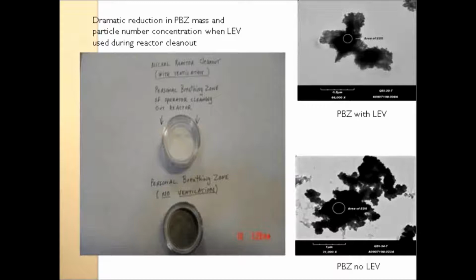Whereas when they didn't use it, look at what happens. This is breathing zone samples. You can see the material is much larger, and these were all confirmed with EDS for the material of interest, so we had a nice spike for nickel. We knew that's what the particle was when we were doing the cleaning.